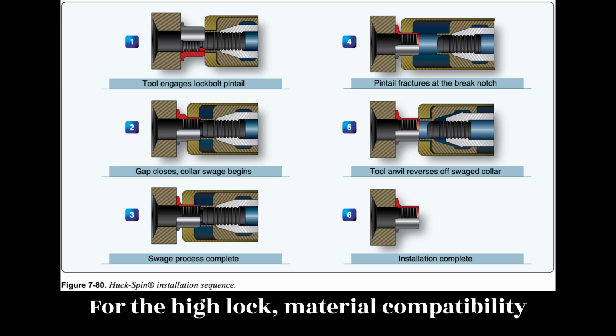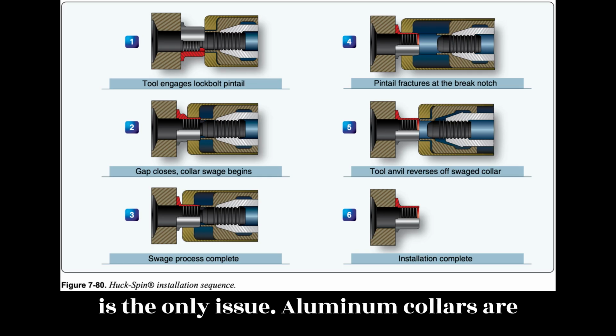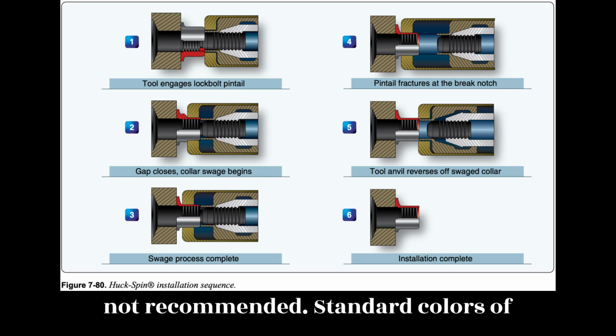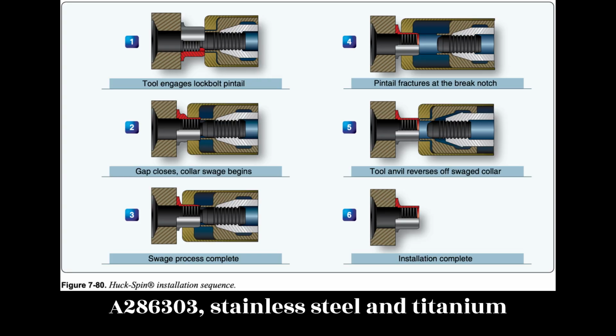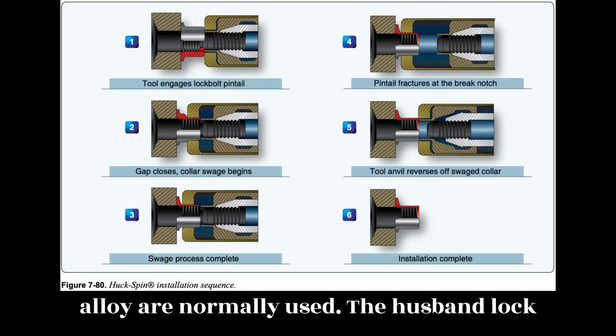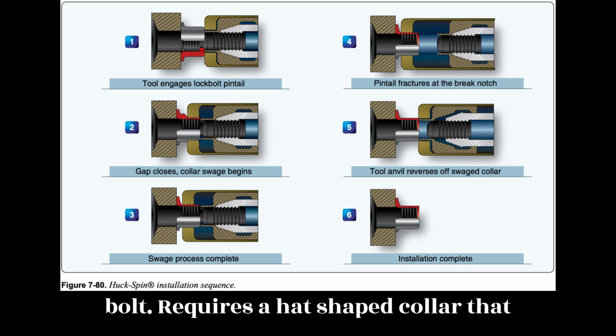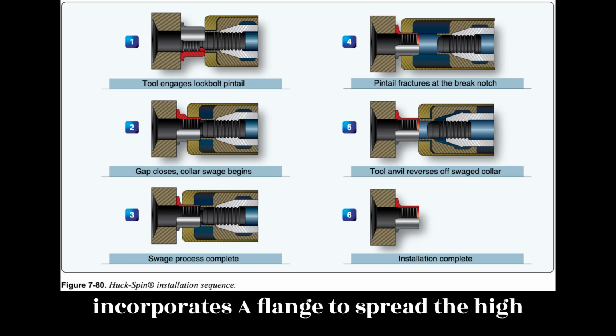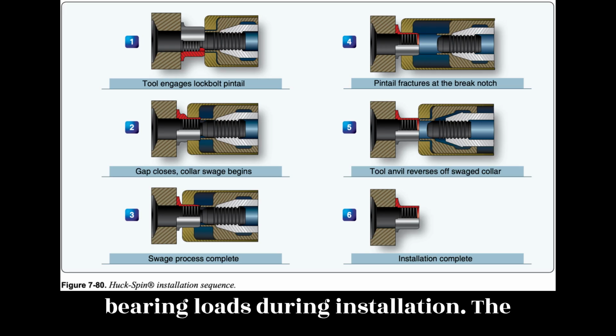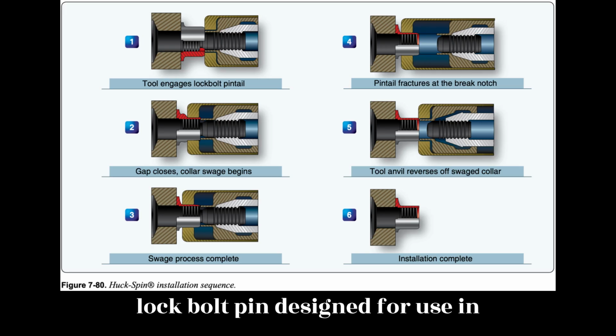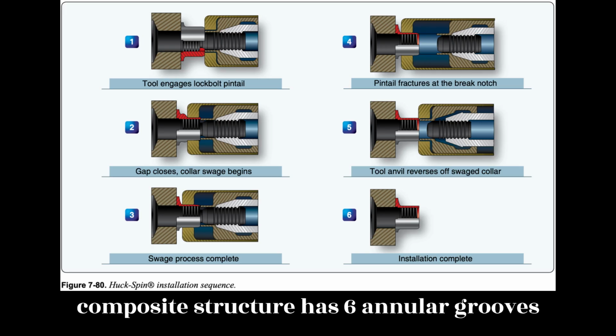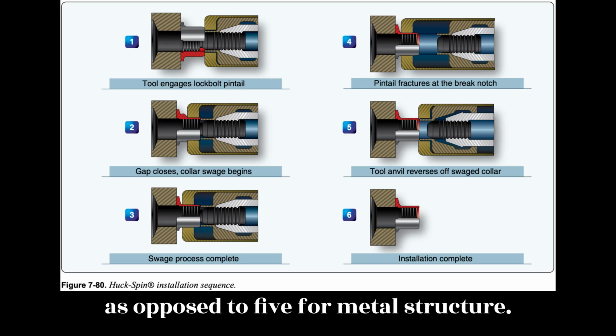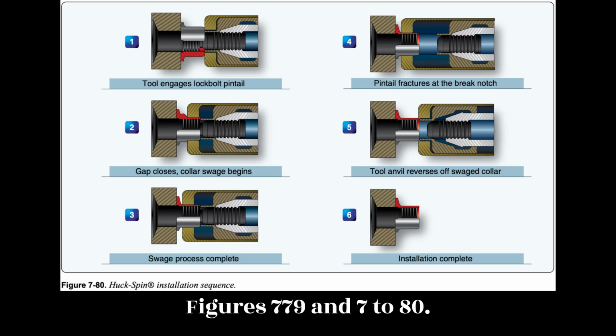For the Hi-Lok, material compatibility is the only issue. Aluminum collars are not recommended. Standard collars of A286, 303 stainless steel, and titanium alloy are normally used. The Huck-Spin lockbolt requires a hat-shaped collar that incorporates a flange to spread the high bearing loads during installation. The lockbolt pin designed for use in composite structure has 6 annular grooves as opposed to 5 for metal structure. Figures 7-79 and 7-80.